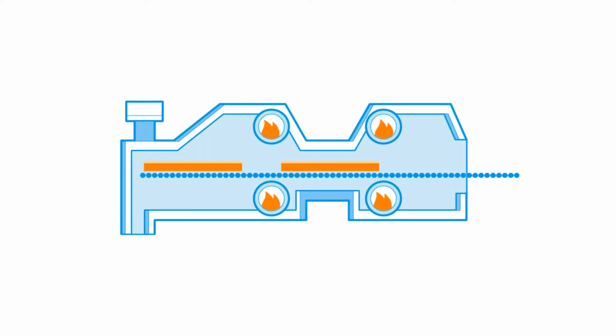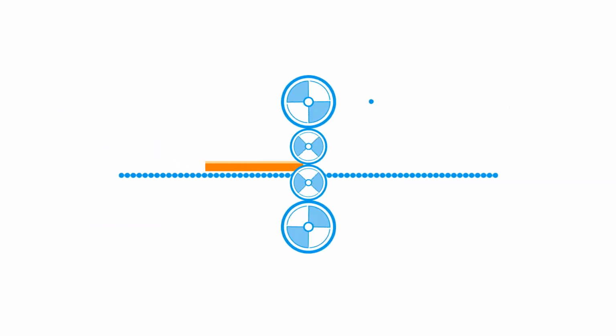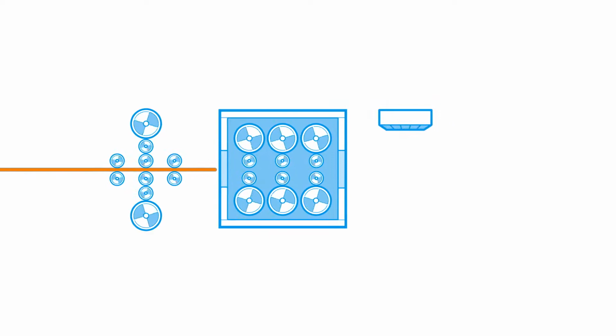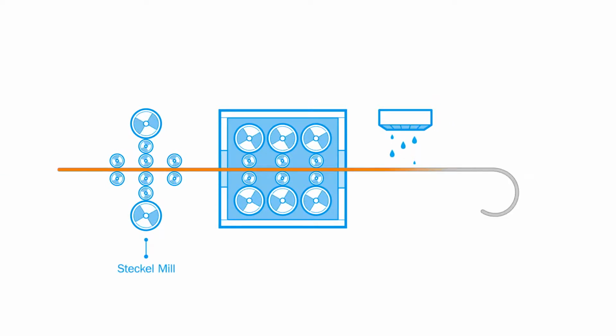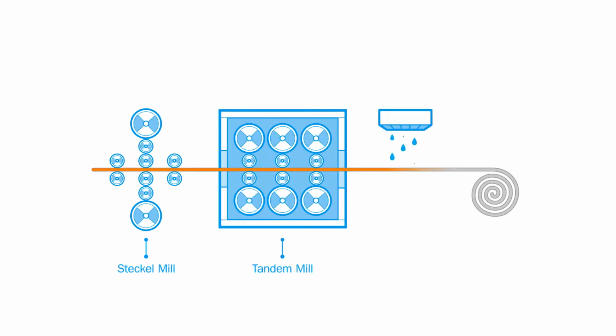The slabs are first transferred to a walking beam furnace, in which the temperature of the steel is raised to more than 1200 degrees Celsius. The slab is then rolled backwards and forwards a number of times through a roughing mill, reducing its thickness and increasing its length and transforming it into a transfer bar. Passing the transfer bar through the Steckel and tandem mill further reduces its thickness. It is then coiled and moved to a cooling pool.